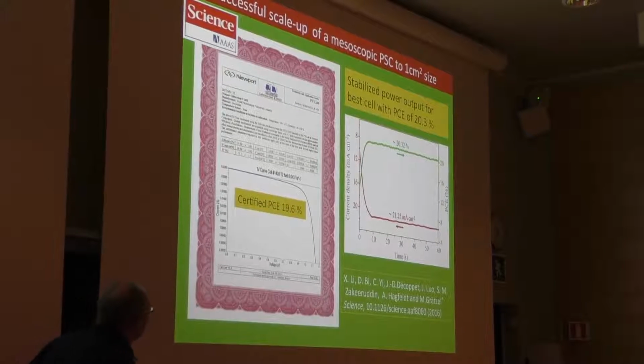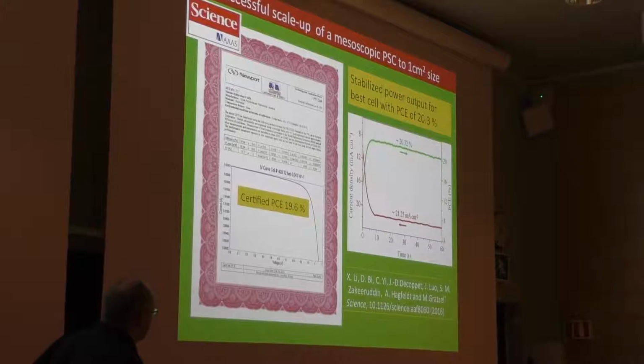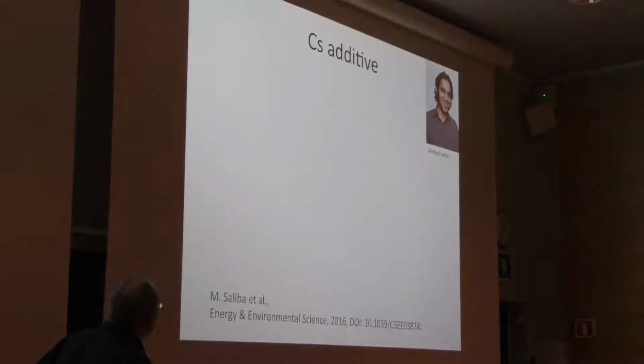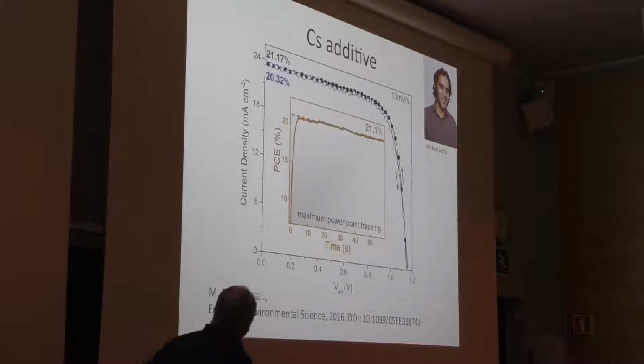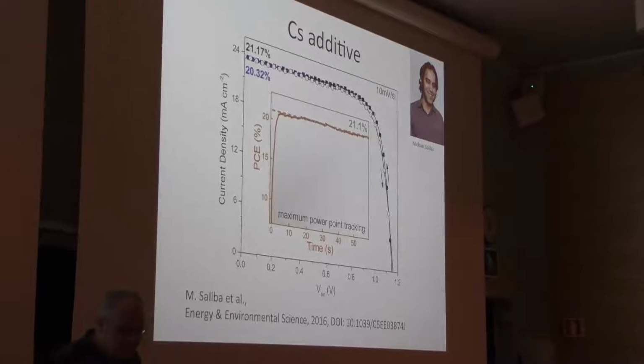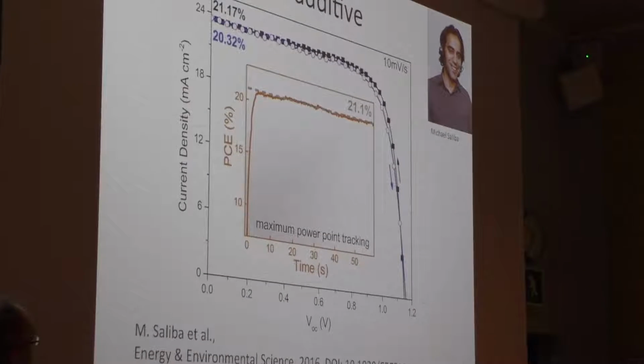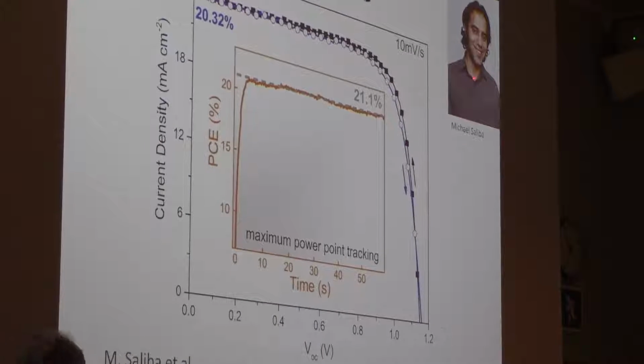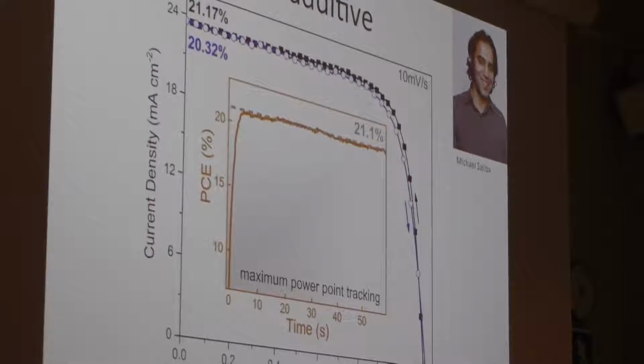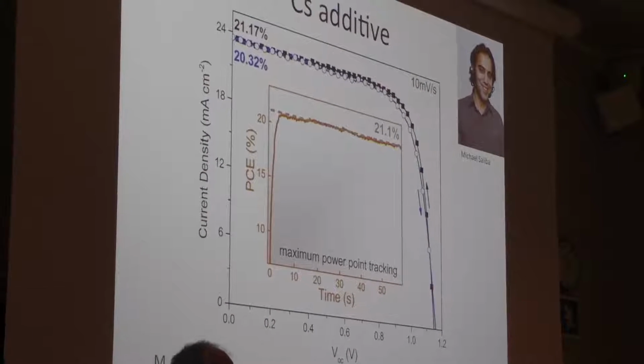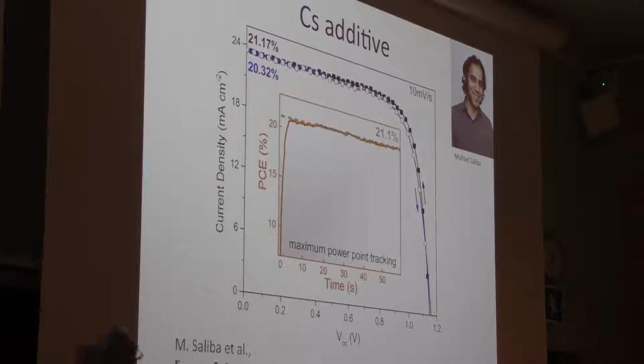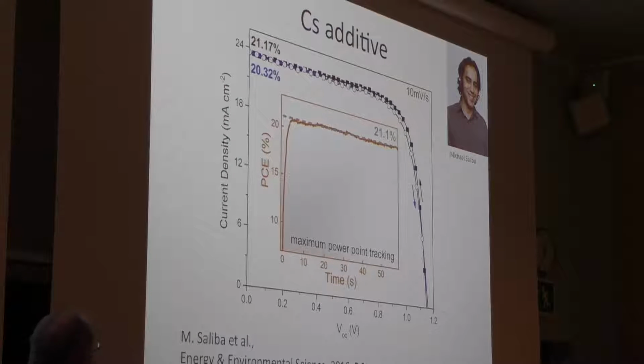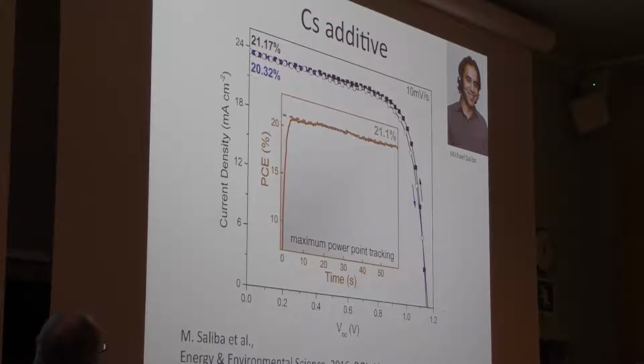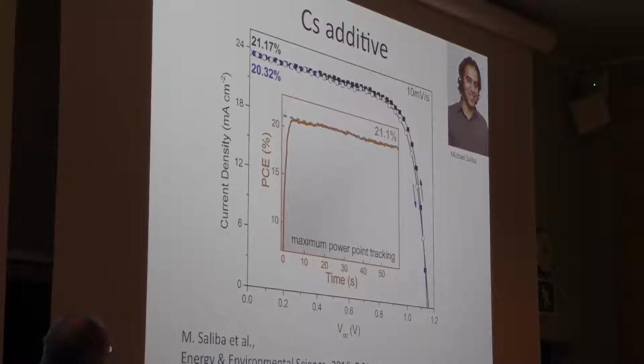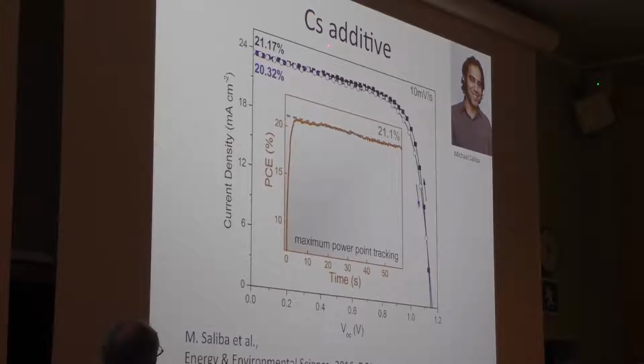So, but anyway, it shows also that you can have larger cells. We have continued the path about mixing, and it's an interesting concept. So Michael Saliba, postdoc here at EPFL, saw that some work started with inorganic cations also, like cesium, having a bit better stability, and he added then cesium to our mixture. So this is now 3 cations: cesium, formamidinium, methylammonium, in the mixture iodide bromide.